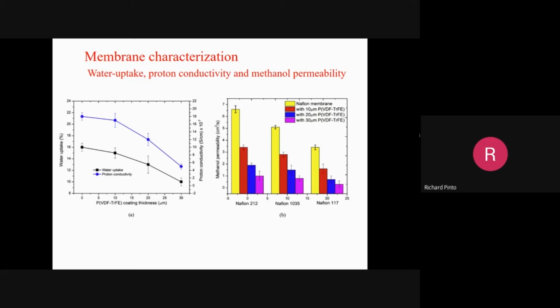But if it's a thinner membrane, you get higher membrane permeability, which is not desirable. Membrane permeability is on the y-axis here, Nafion thickness here, and permeability decreases as you increase the thickness. But at the same time, if you put 10 micron, 20 micron, 30 micron thick PVDF-TrFE, permeability goes down.